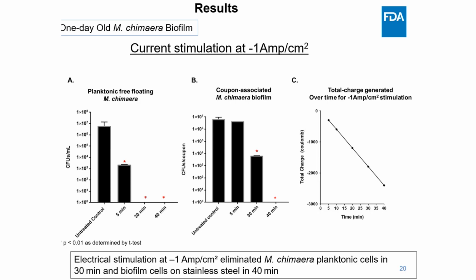One of the striking findings was the high sensitivity of planktonic NTM cells to electrical current. With just 5 minutes of stimulation, we observed a significant reduction in planktonic viability. By 30 minutes of treatment with minus 1 amp current density stimulation, we were able to completely eliminate these planktonic bacteria compared to the untreated control. Even more compelling, we found that applying minus 1 amp current density for 40 minutes was sufficient to completely eliminate 1 day old biofilm, results that far exceed the performance seen with voltage alone.